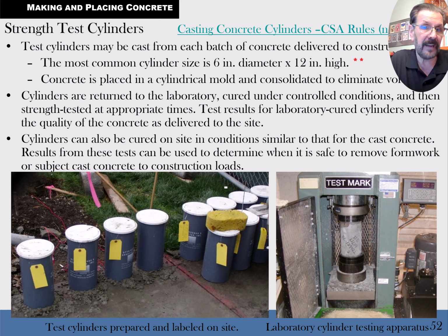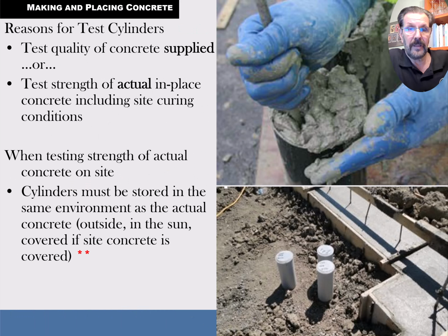So you might have 85,000 pounds that it takes to break that cylinder, but when you divide out the 85,000 pounds by the number of square inches on a circle, on a 6-inch circle, for instance, that'll tell you what the actual compressive strength is. Now, there are also testing cylinders that are 4 inches tall, 4 by 8 instead of 6 by 12. And so those ones generally we fill half full instead of still 4 inches each time, and we'll plunge the rod 25 times and another half full to go with that. So here they are plunging the last little bit here before they put it out.